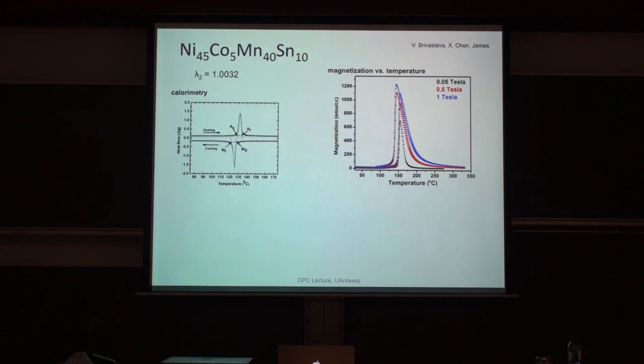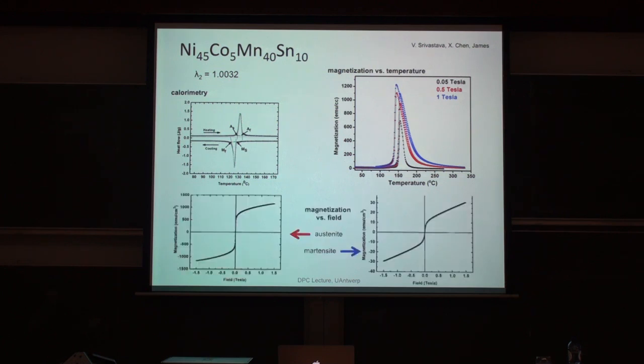But this is quite interesting material because the martensite phase is non-magnetic. And by the way, this class of alloys and the first measurements were done by people also visiting this ESOMAT conference, in particular Professor Kainuma from Japan. And this is a related alloy. But this is a really spectacular one because the martensite phase is non-magnetic. You go through the phase transformation and it becomes a magnet. But not only that, you probably don't know this unit, but it's 1200 EMU per centimeter cubed. That's a really strong magnet, almost the strength of iron at that temperature.